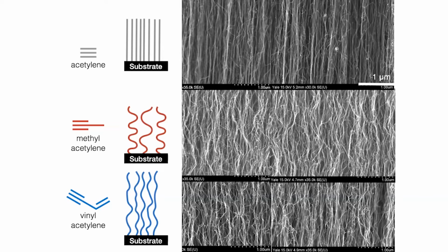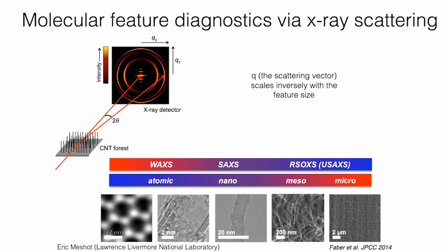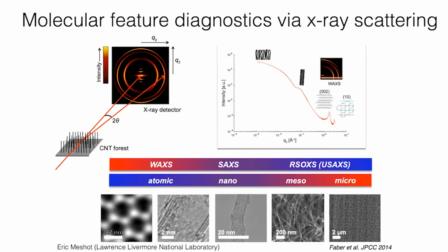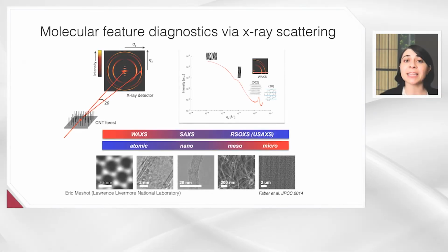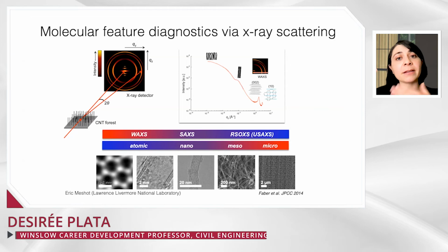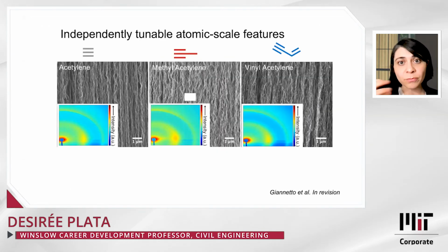Now, we wanted to be more quantitative and rigorous about this assessment, and so we turned to a technique called X-ray scattering. So using small and wide angle X-ray scattering, we are able to see molecular scale features of the structure. A beam of X-rays can be impinged on a well-aligned carbon nanotube forest, and the degree of scattering of those X-rays is inversely proportional to the feature size that you're interrogating. So something we call Q, the scattering vector, can report on the molecular and atomic scale features within a carbon nanotube forest. So we can extract things like alignment, interwall spacing, and the molecular structure of the rings themselves.